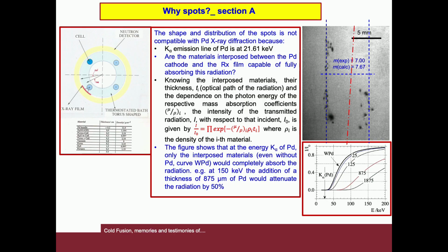As an example, if we put ourselves at 150 kiloelectronvolts, the presence of a thickness of 875 microns of palladium would attenuate the radiation by 50%.